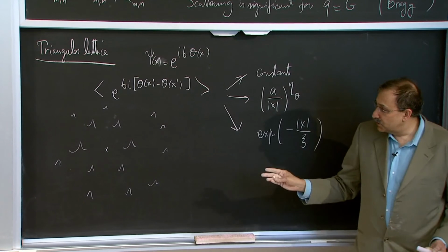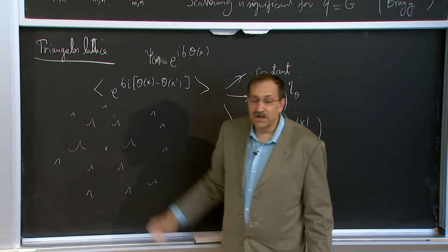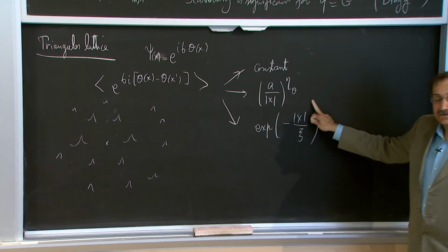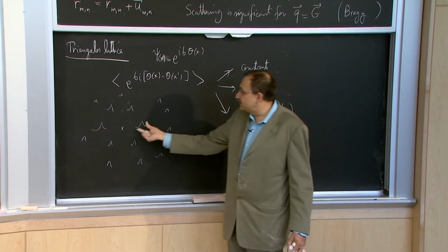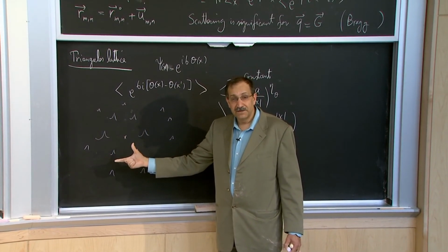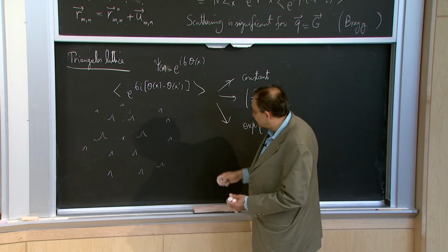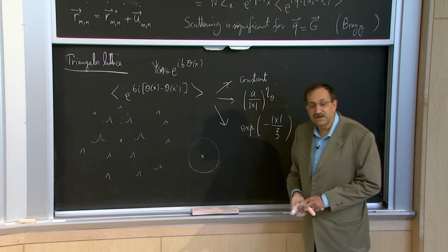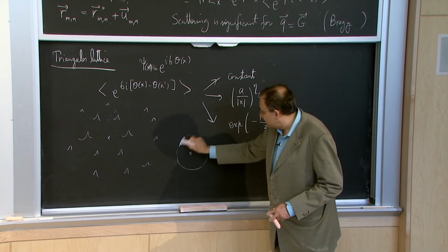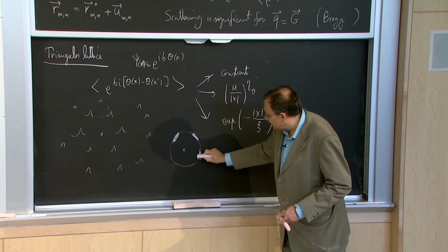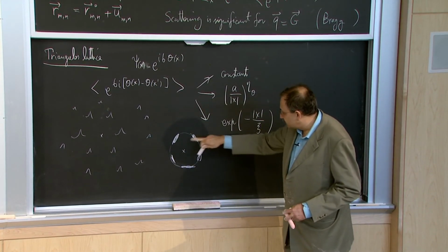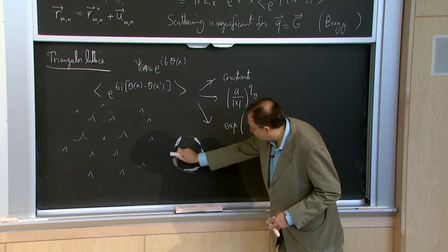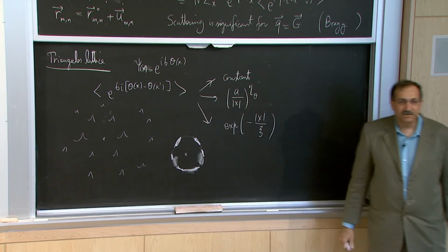But now you can see that this picture clearly has a very well-defined orientational aspect to it. Now, once we go to this intermediate phase, all of these peaks disappear. But what you find is that when you look at this, rather than getting a ring that is uniform, you will see a ring that has very well-defined variation, 1, 2, 3, 4, 5, 6, 6-fold symmetry to it.